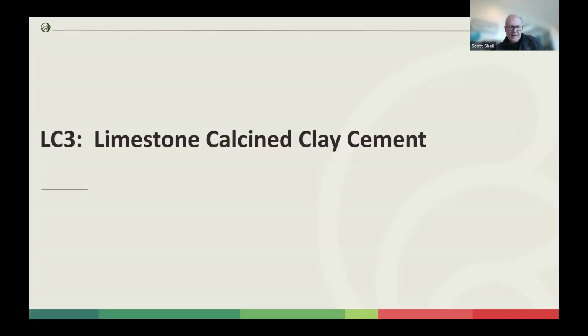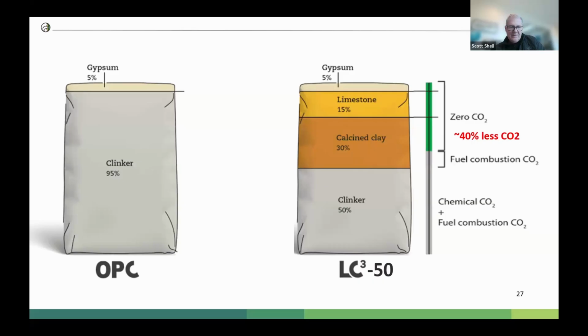So let's take a closer look at LC3. It's a mixture of ground limestone and calcined clay and cement. On the left, you see OPC, or ordinary Portland cement. And on the right, you see LC3. This is LC3-50 with 50% clinker. So you replace about half of that clinker with 30% calcined clay and 15% ground limestone.